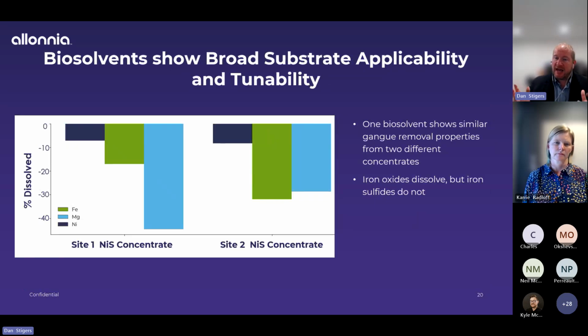And where we see that of kind of interest is that while we gave a case study with a particular substrate, we're now looking at other nickel sulfide substrates that we found across the globe. And we're actually getting reasonably similar data. Right? At the end of the day, the mineralogy has some similarities and some differences, but in these instances, we're able to still remove a good amount of iron and remove a good amount of the magnesium.